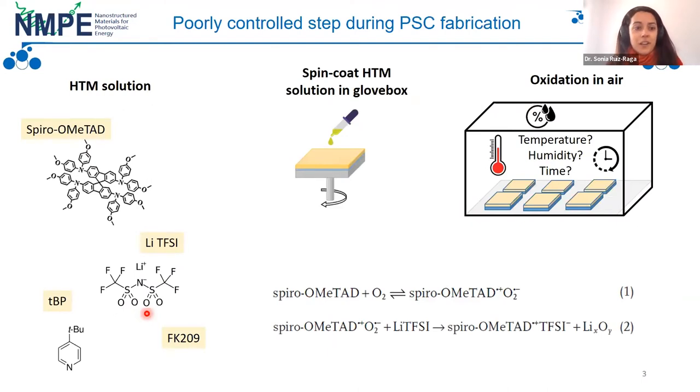Everyone that's doing perovskite solar cells knows that the spiro-OMeTAD is a tricky layer in the device because it's very poorly controlled. In order to gain high conductivity, we have to add additives, which are the usual ones. And even if we spin coat the hole transport material in the glove box, we have to take it out to air to become oxidized and increase the conductivity. So we have some uncontrolled variables: the temperature, the humidity, and the time. The spiro-OMeTAD becomes oxidized and some byproducts are formed. And there is another uncontrolled parameter: some water or oxygen can penetrate into the perovskite and start the